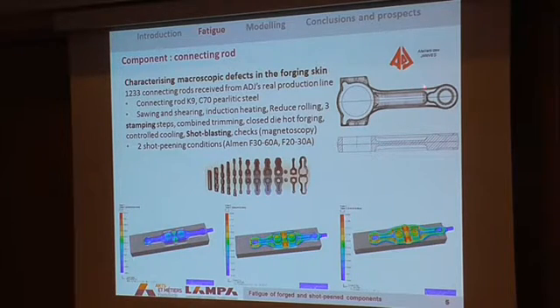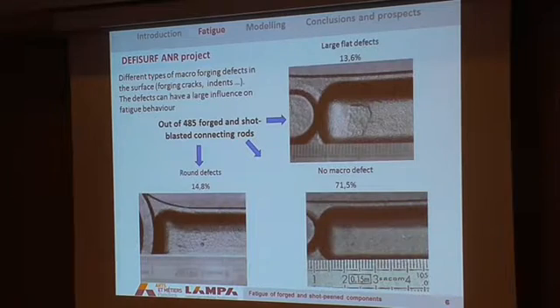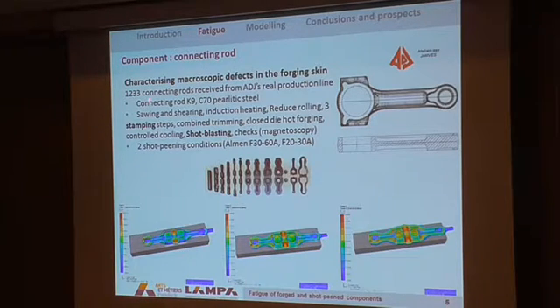Okay, about the component under interest, it's that kind of component, a very well-known connecting rod made of pearlitic steel and obtained with several stages. We have stamping steps, shot blasting steps, and we observed something very interesting. What's specific about this work is that we used a huge number of connecting rods here to make statistics directly extracted from the production line.